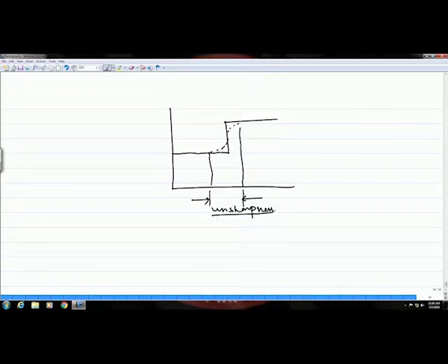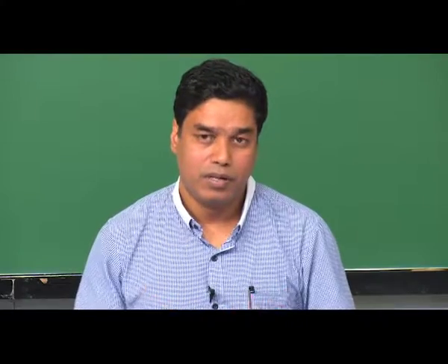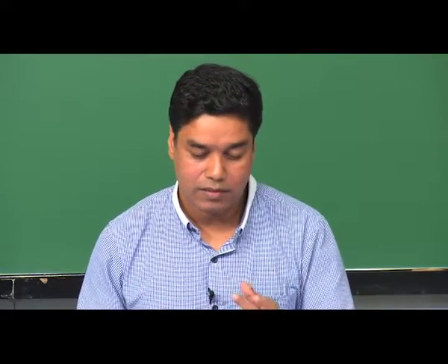Okay. So, this inability to reproduce this boundary properly, as we defined just now, is known as the unsharpness of the image. Okay. And this primarily happens due to the focal spot size of the machine. So, X-ray machines come with a focal spot which has a finite size, and it is not a point source, right. So, when you have a focal spot with a given size, it will act as a multiple point